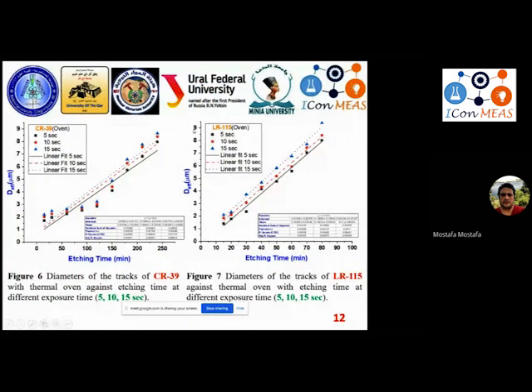We can also measure the diameter of tracks. It's a very important parameter for determining the activity and the properties of the detector. The diameter of tracks for each exposure time is plotted with time of etching, and a linear correlation is found, with fitting parameters for the CR detector and for the LR detector.